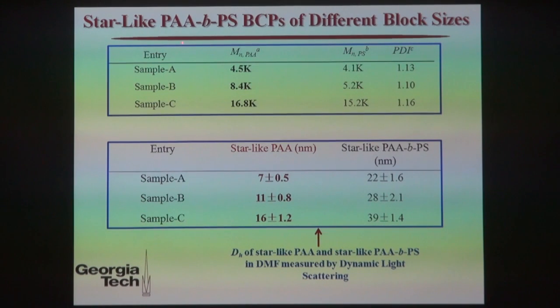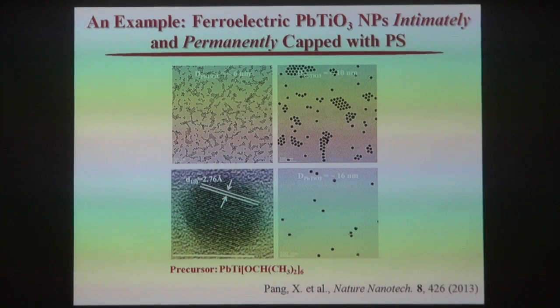So now we took these three star-like block polymers and used them as the template or nanoreactor. And we did the first demonstration by adding lead titanium isopropoxide as the precursor for ferroelectric lead titanate nanoparticles. So what we got is 6, 10, 16 nanometer size nanoparticles. So these sizes were templated from the star-like block polymer I just introduced. You look at this particle. Actually, the surface of the particle is permanently capped with polystyrene. So this high-resolution TEM image coming from this 10 nanometer titanate nanoparticle shows high crystallinity.